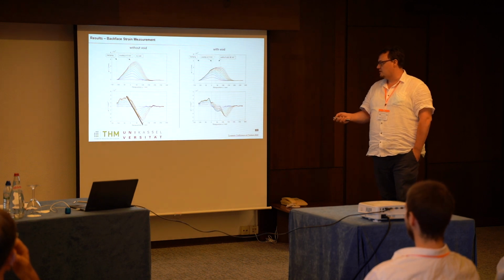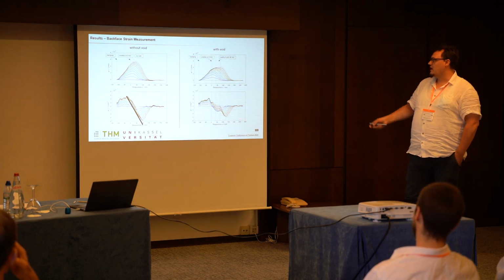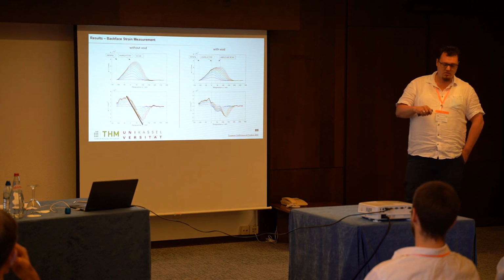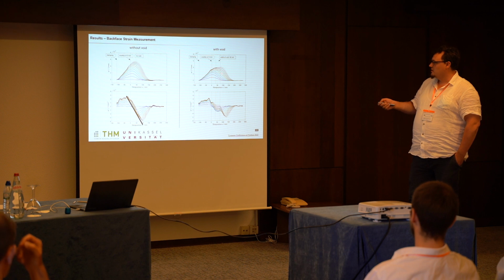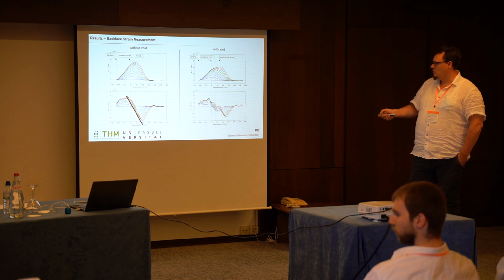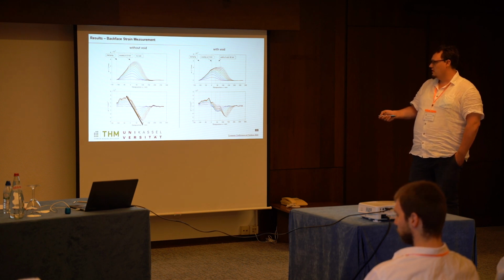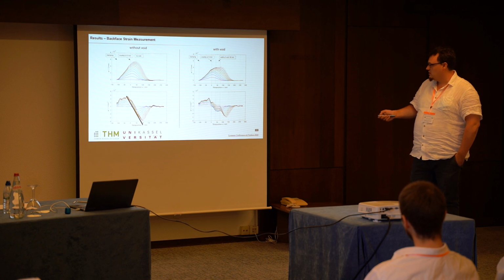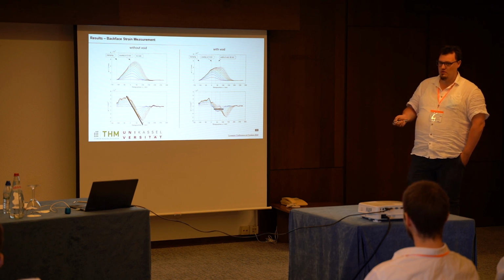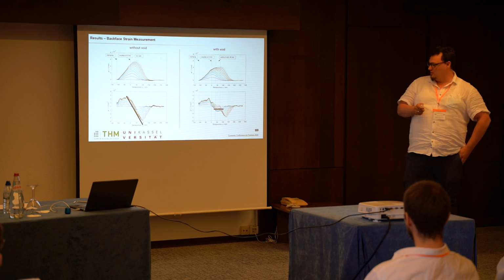This is the reference, and on the right side you see the same diagrams for the specimen with void. You see the values for the second derivative are smaller, and below you see the third derivative of these, and in the middle, where the position of the void is, you can see constant values. I think that matched very well.